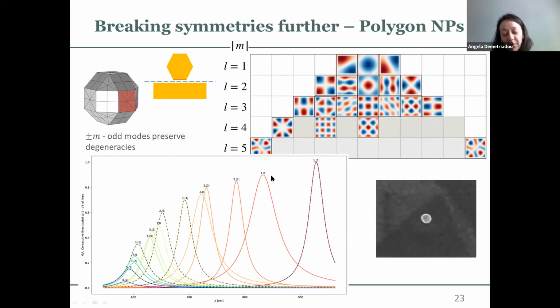And what you see is the breaking of the degeneracy between your modes. So this mode here is the 1,0, and this one here that sits energetically at lower frequencies is this and this mode. And for this particular facet, assembled opposite to the mirror, this and this mode are degenerate.